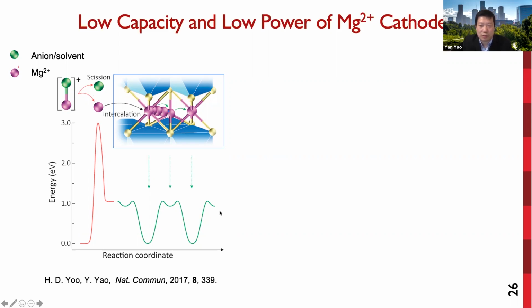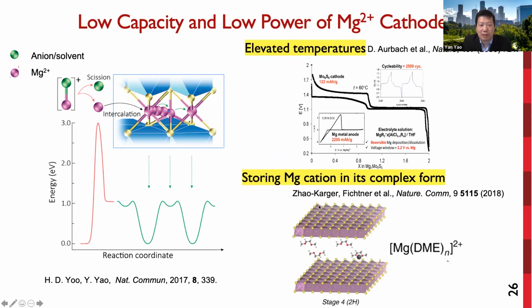So there are two approaches to address these challenges. The one is to cycle the battery at an elevated temperature, for example, 60 degrees C. Doron Aurbach's group has shown that the Chevrel phase can reach theoretical capacity. The other approach is to store magnesium ions in their complex form, such as using DME molecules to solvate magnesium ions. Both approaches have disadvantages because elevated temperature would require a heater, which is not very practical.